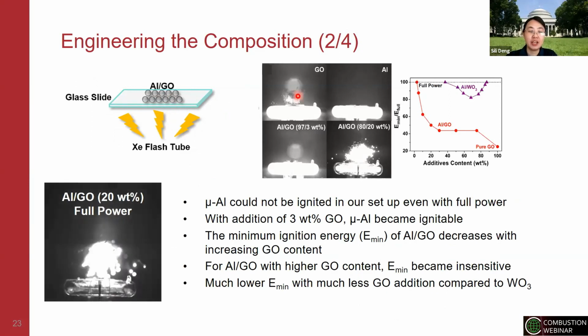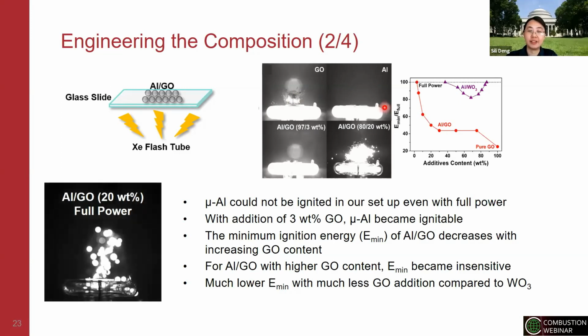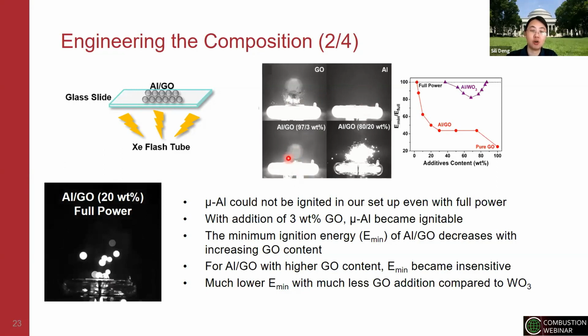And what we could see here is that upon the flash, right, GO can be ignited. However, if we are using just pure aluminum, they cannot be flash ignited. And just by mixing only 3% by weight of GO, aluminum can be ignited. So just with 3% of addition of GO, we can see the ignition of aluminum. And with 20%, you can see the ignition is actually very strong. And compared to GO itself, because after ignition most of the heat release comes from aluminum, you can see it's really strong.